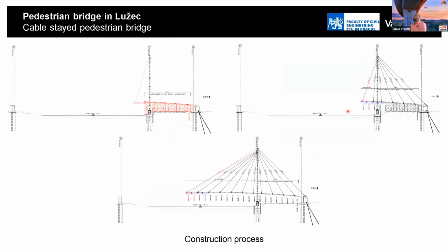Interesting was also the construction process, because, as I said in the beginning, it was a combination of casting of some parts of the superstructure. Then we used special temporary supports for some number of segments, and the rest of the structure was realized by the balanced cantilever. So this is the first stage. You can see the temporary scaffolding, and some UHPC elements were placed in this area in the right position, and also the connection between the UHPC element and this cast in situ element, which is directly connected to the abutment, was realized in this phase.